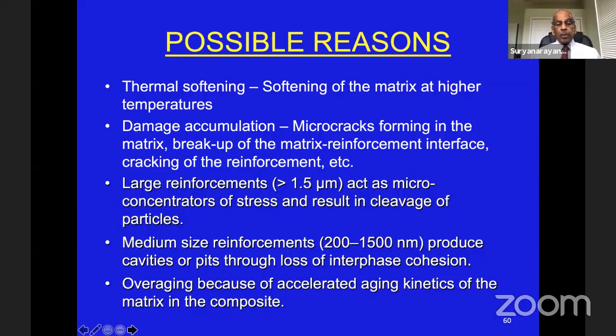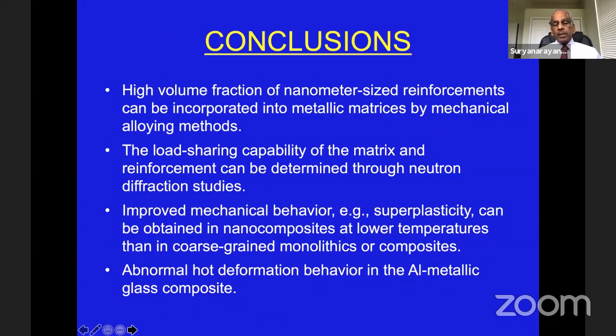So to conclude this nanocomposites area and in general, high volume fraction, as I said, up to 60% we were able to get. The load sharing capability was determined using neutron diffraction studies. And then mechanical behavior is in general improved. Superplasticity is observed, and a very abnormal behavior, where the matrix seems to be stronger than the composite, is observed in some of these types of composites.